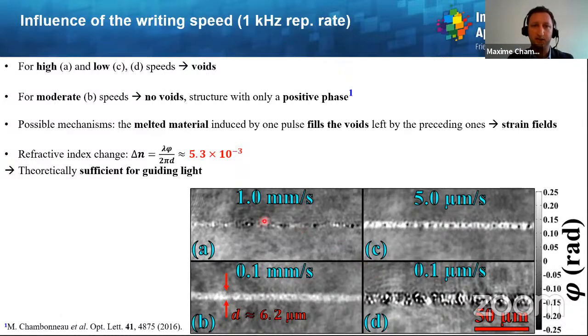What one can see is that for high and low speeds, you can see some black dots in the phase images, which are related to some negative phase shift, meaning that there is some negative index change, which has to be related to voids or microcavities inside the material.